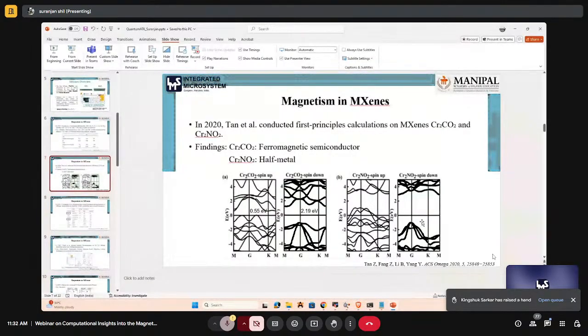So your question is why there is such a significant difference, compared to this being a semiconductor. This is a half metal. If you see these two structures, this one is only chromium carbide with oxygen termination, and this is chromium nitride. So it's my belief that in chromium nitride the hybridization comes from the electronic structure. The hybridization of chromium and nitrogen, and when we terminate with oxygen, that makes a huge difference. That's the main difference which can give you these results. That's what I know, but I think you can go to this paper and see that. This is not our paper, first of all. Okay, sure. Thank you.